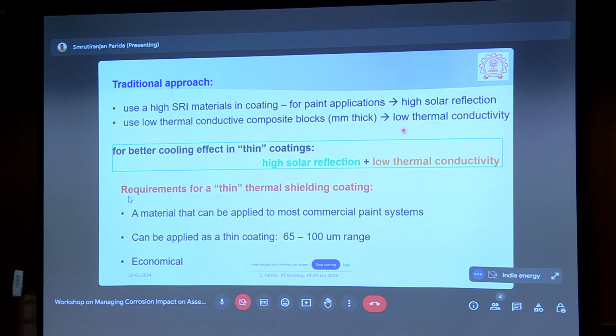This is where we tried to change a few things. We completely changed what traditional people are doing, and that is how we got a novel coating which can shield the solar heat, reducing the temperature by up to 21 degrees. So the combination of solar reflection and thermal conductivity is what we worked on. One of the other criteria we set for ourselves is that the material can be applied in most commercial paint systems. That means it doesn't matter whatever resin or application method we choose, we simply add this material to that paint system and then we pass.